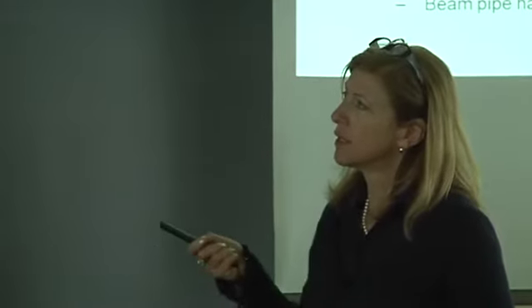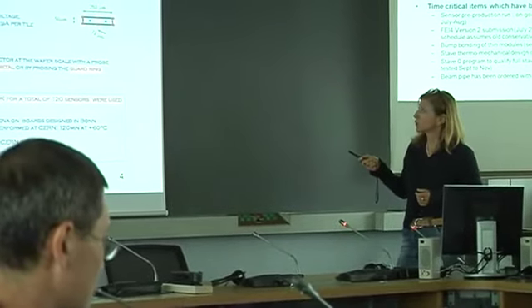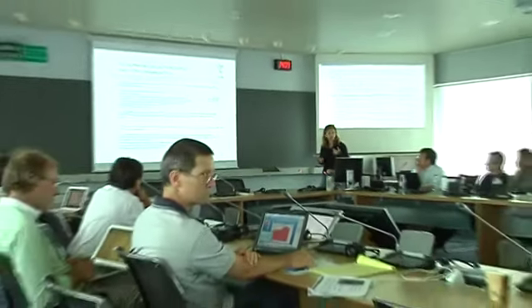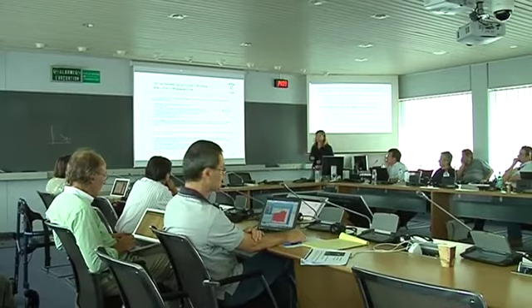By the way, I should stress that the dimensions and the layout of electrodes for the pixel IBL sensors is with 2 electrodes per 250 microns. Incidentally, I should say that we could also increase the number of electrodes, and this would increase radiation hardness because it goes, of course, with the inter-electrode spacing.